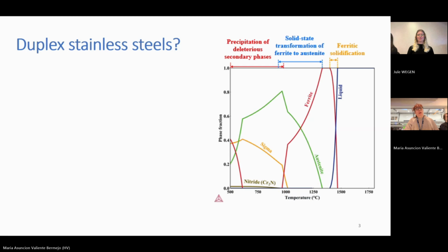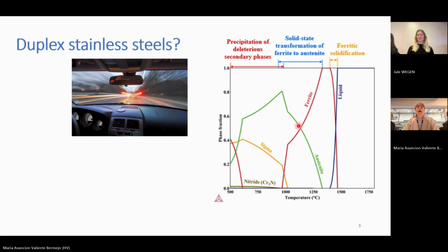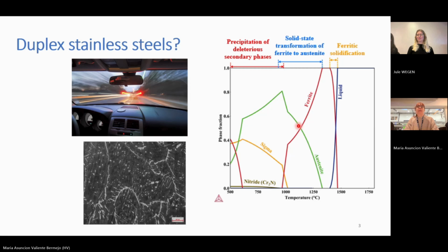If we look into the phase diagram, the diagram under equilibrium, we will see that duplex, let me find the pointer now. Yes. So when the material solidifies, it's fully ferritic, basically fully ferritic. And then if we give time and opportunity, part of the ferrite will transform into austenite. And the ideal point is that we get this 50-50%, so 50% austenite, 50% ferrite. But what happens if we cool very fast? I mean, if we have a very fast cooling and we don't let the material solidify under equilibrium conditions, what we get is basically a fully ferritic microstructure.